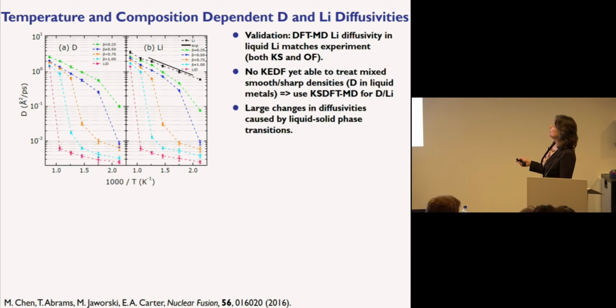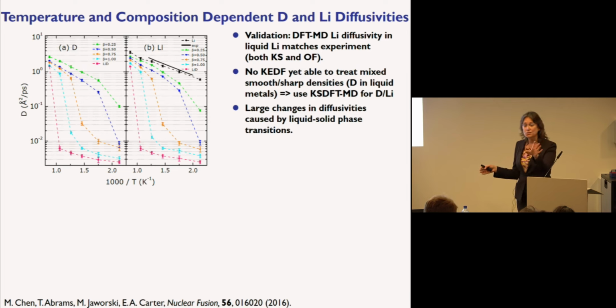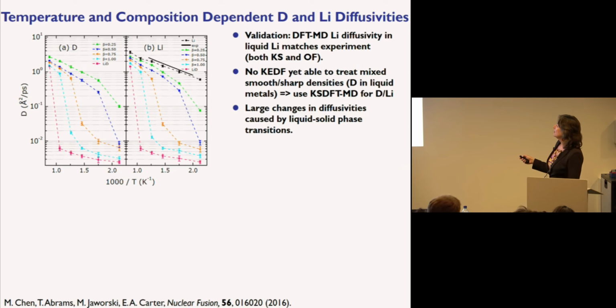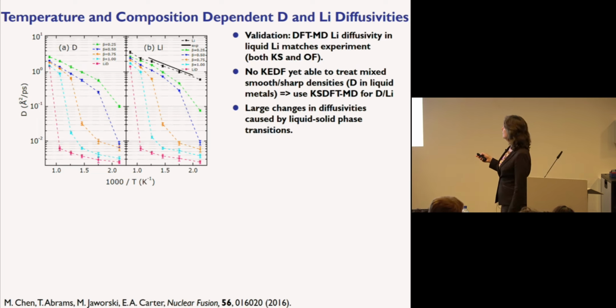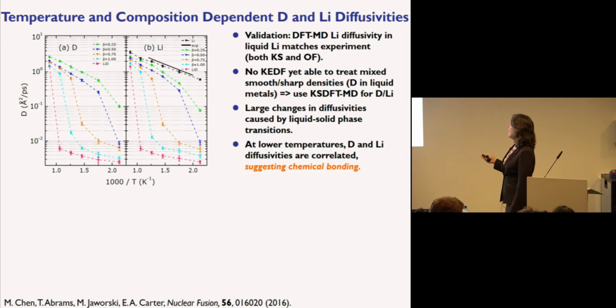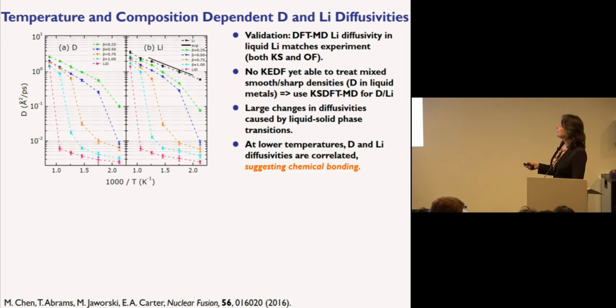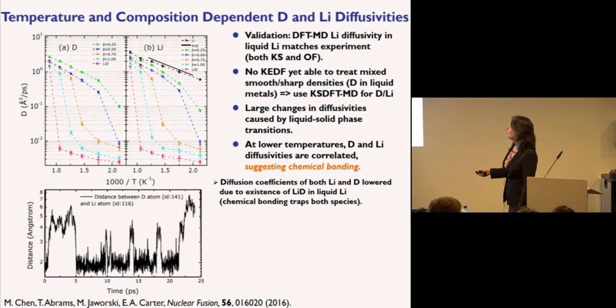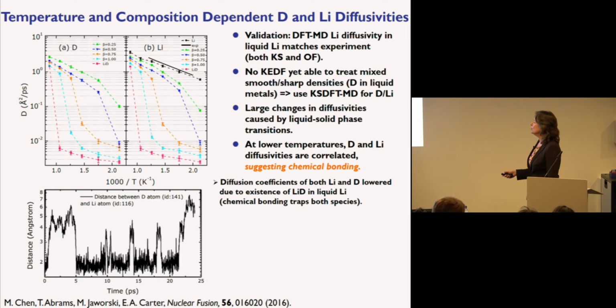The large changes in diffusivity, and these are predictions, by the way. There's no experimental data for this point, but we are predicting large changes in diffusivities that are caused by liquid-solid phase transformations. We can see it in snapshots that we can examine in the trajectories, and essentially at lower temperatures we see that the diffusivities are correlated. They're basically the same, suggesting that there is chemical bonding going on, and we can plot distances between lithium and deuterium atoms at various times. It's fluxional, where you're really creating chemical bonds.